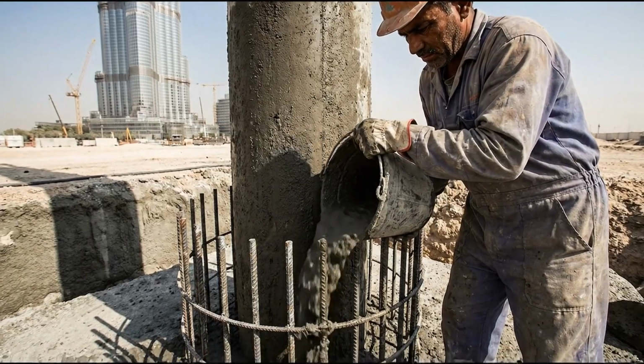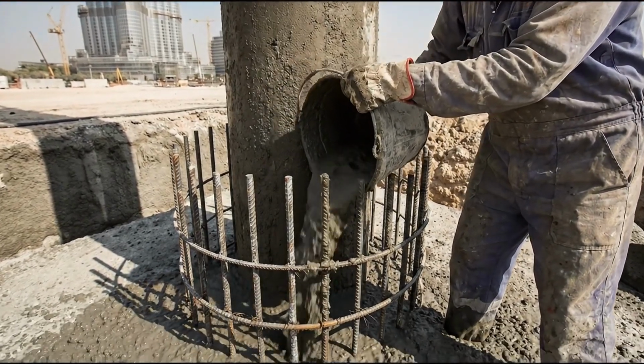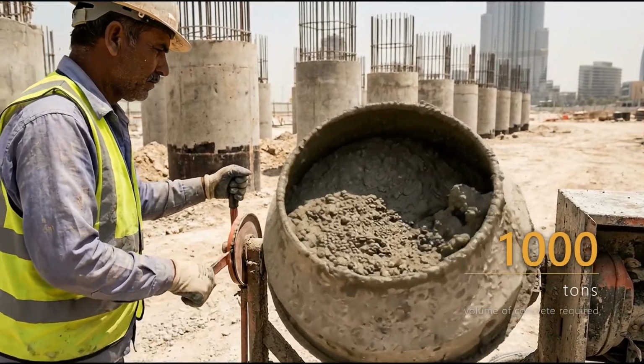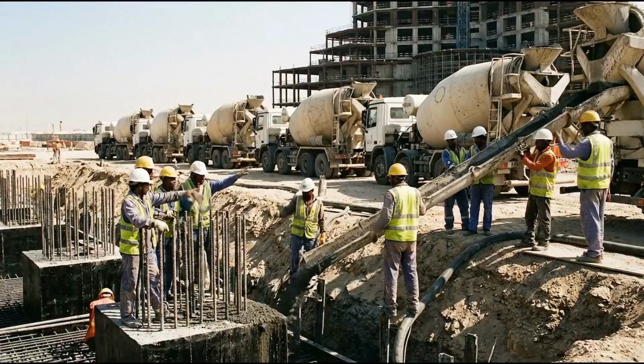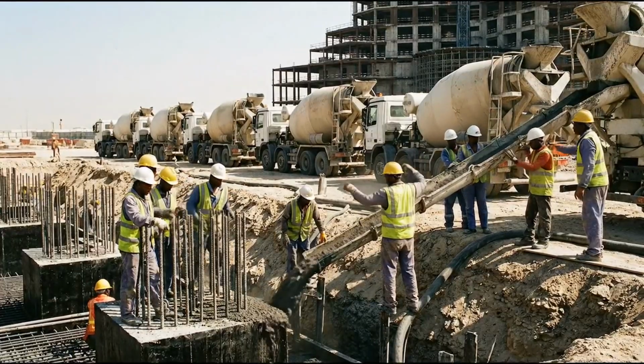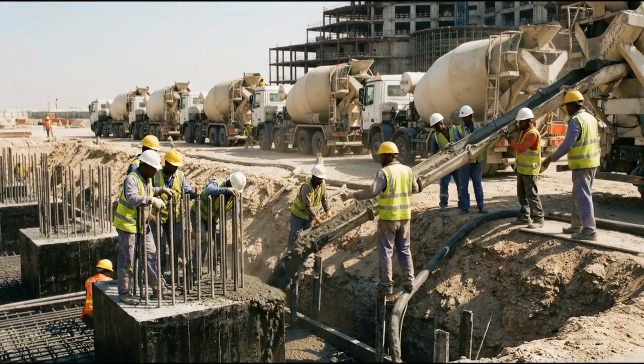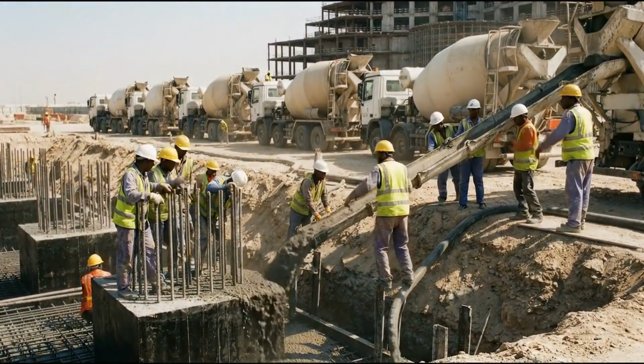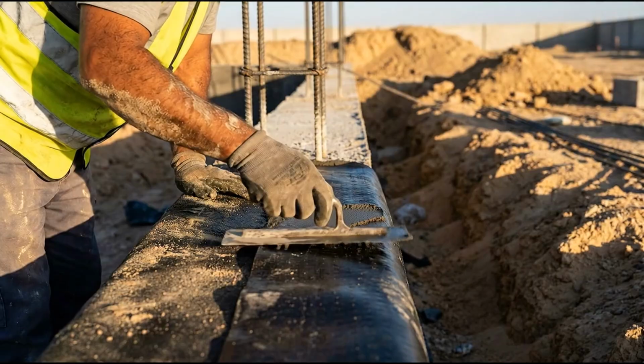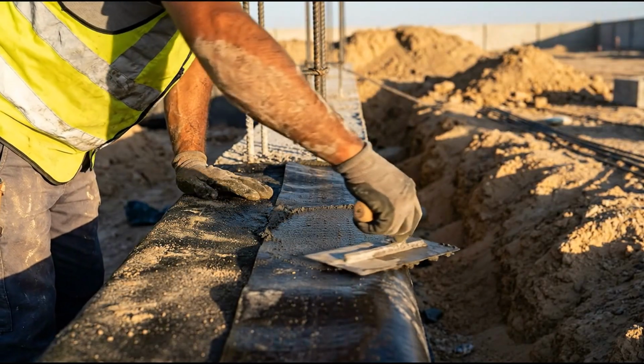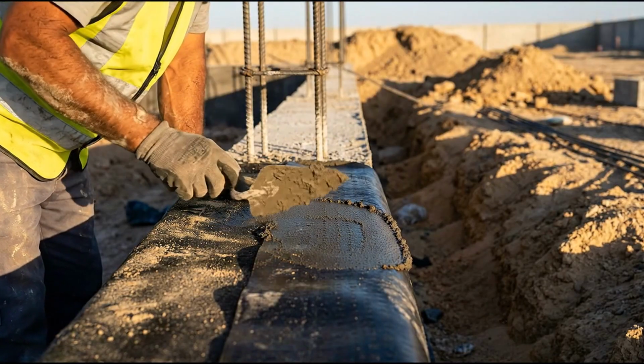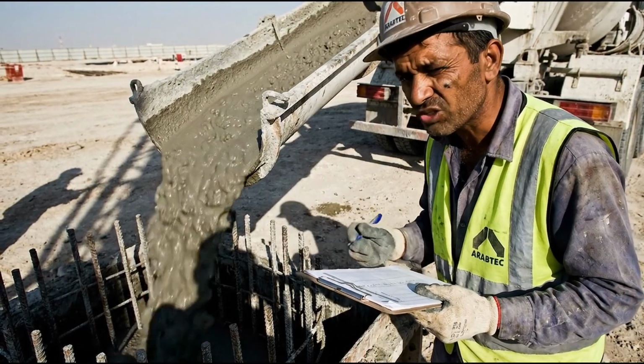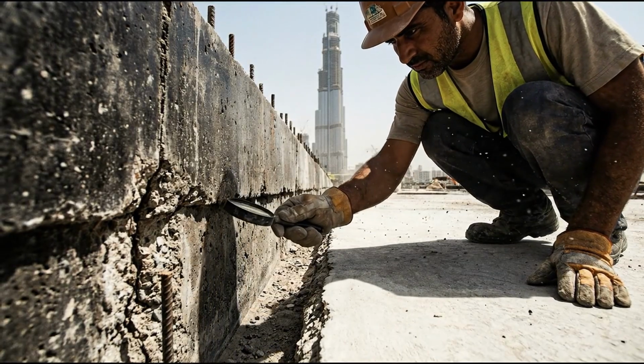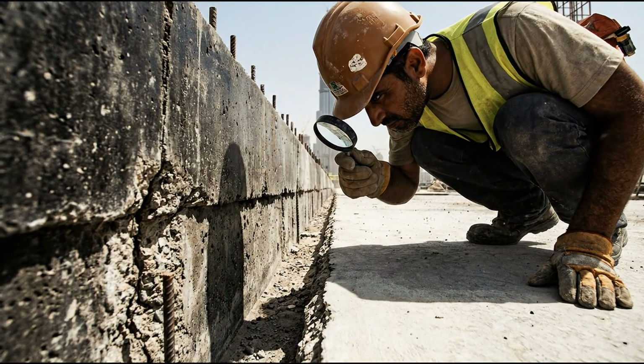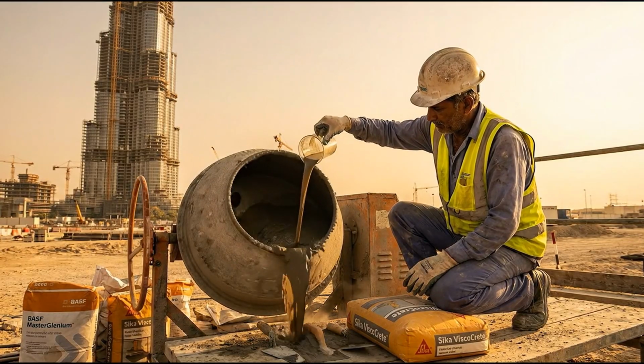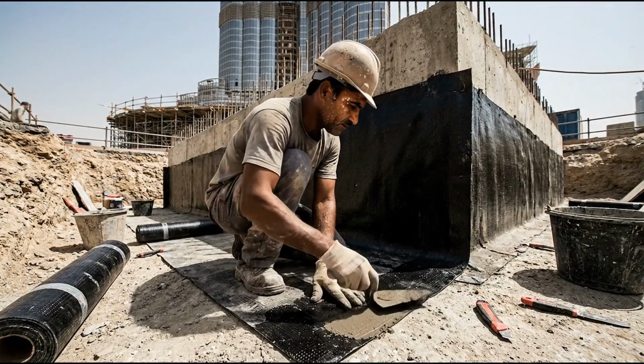Pouring it was one of the most carefully managed operations of the entire project. The volume of concrete required was enormous. Over 12,500 cubic yards delivered and placed in a continuous pour that ran for nearly 4 days straight without stopping. Stopping would have been catastrophic. Concrete cures through a chemical reaction that generates heat, and if a pour is interrupted, the joint between old and new concrete becomes a structural weak point. On a foundation expected to last a century, weak points are not acceptable.